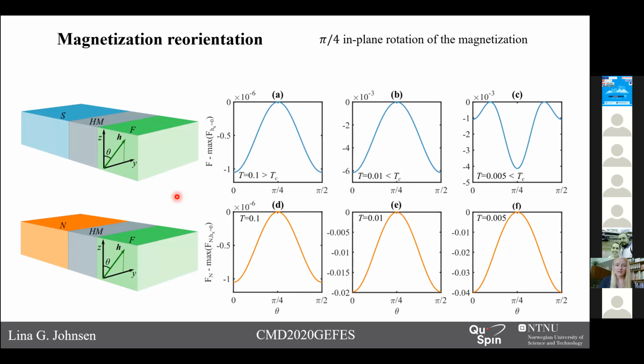We also considered an in-plane rotation of the magnetization, and what we found was that if we are above the critical temperature, as in panel A, and slightly below the critical temperature, as in panel B, we have a preferred magnetization direction along the cubic axis. If we further lower the temperature, so it's well below the critical temperature, a new minimum appears at the pi/4 direction compared to the cubic axis, that is in the 110 direction. So we have a pi/4 rotation of the magnetization.